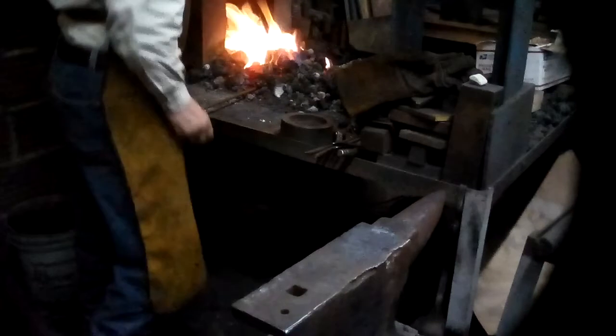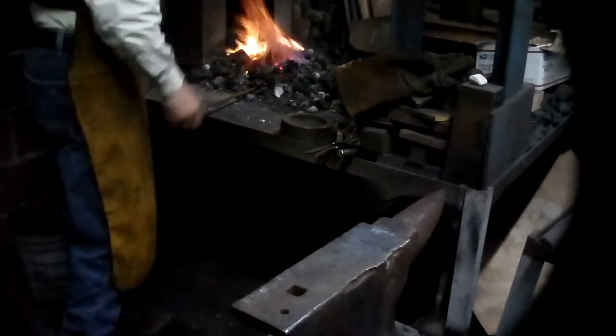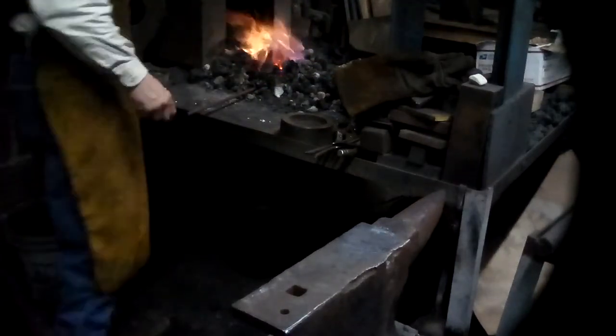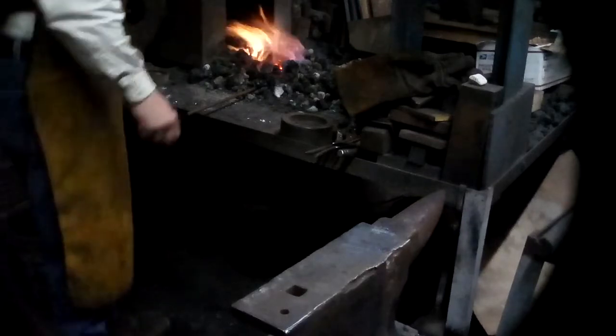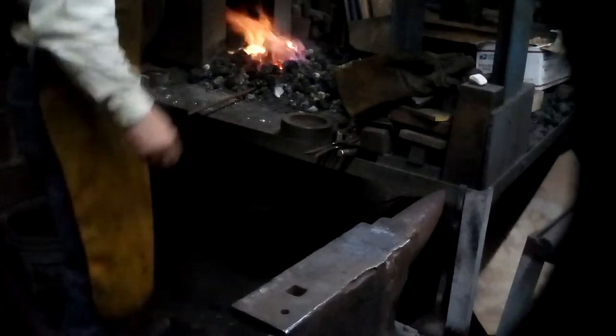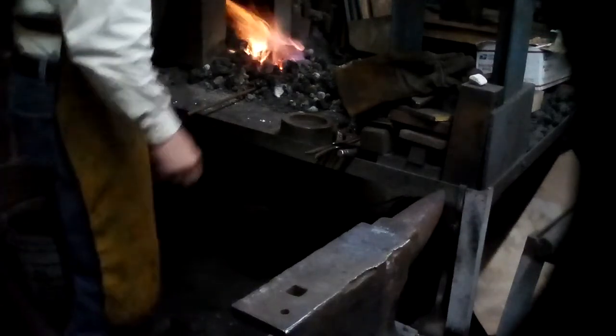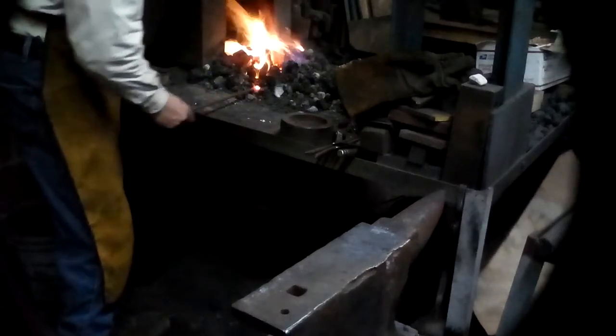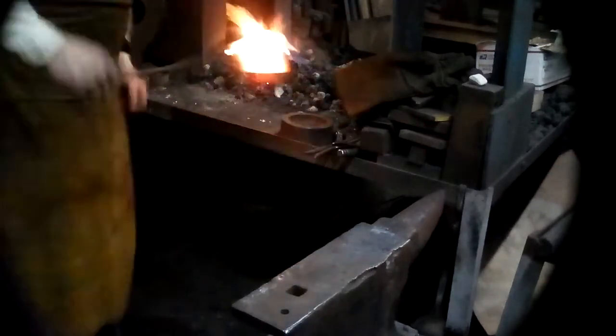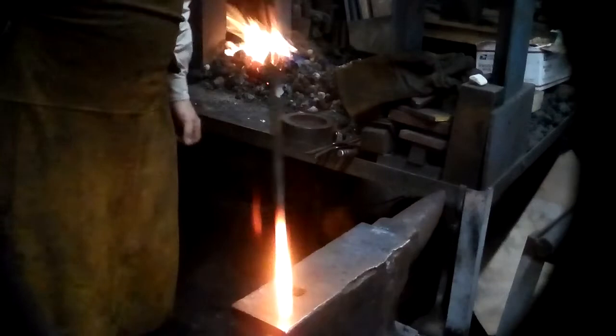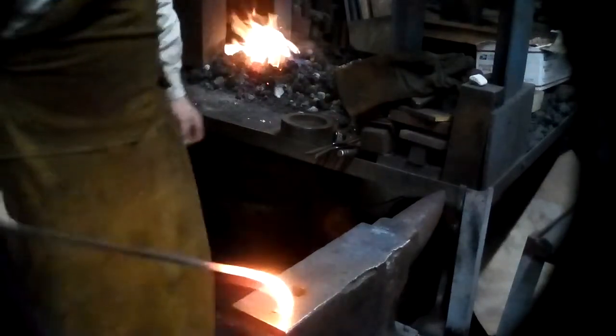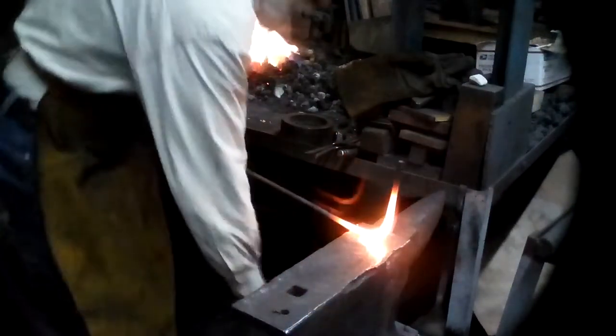Okay, the first thing you should know is that you should have a fairly deep bed of coke with a little bit of green coal on top so that you get an atmosphere that's fairly reducing. And I'm just going to stick this in the hardy hole of the anvil. Bend it over.